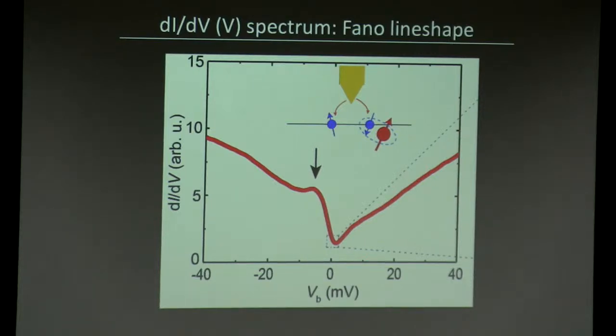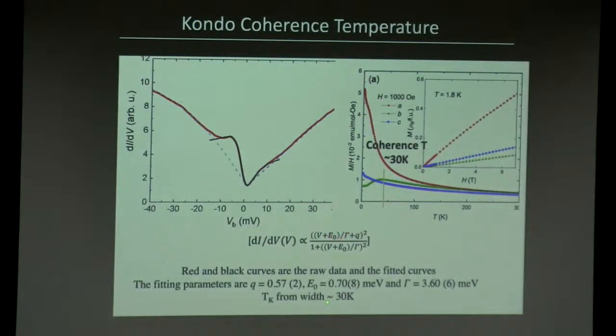So this is what the normal state looks like. This line shape is reminiscent of such Fano line shapes in many heavy fermion systems. By fitting this line shape, you can get many things, including the Kondo coherence temperature, which from our data we estimate to be 30 Kelvin. And that's what you also see from transport.